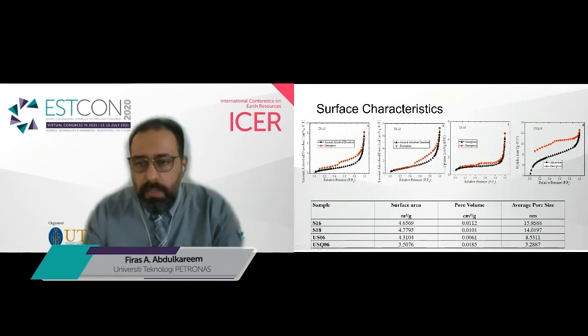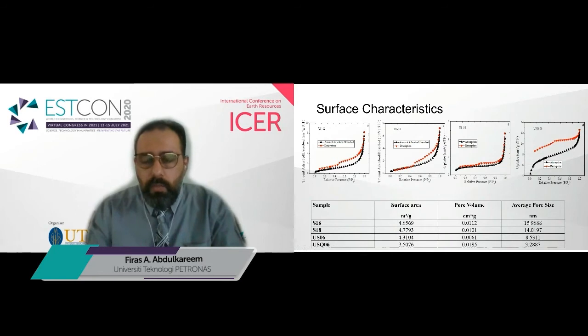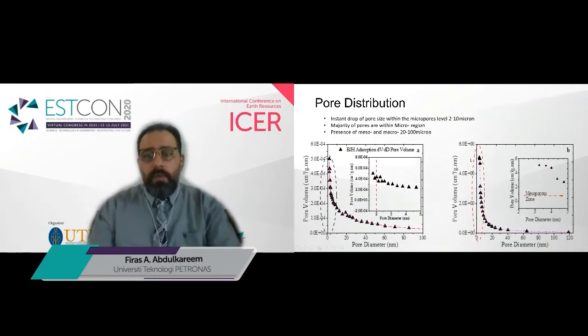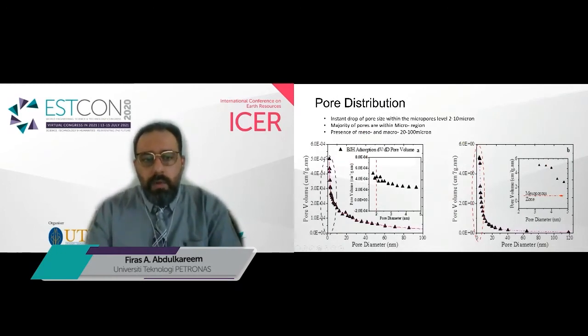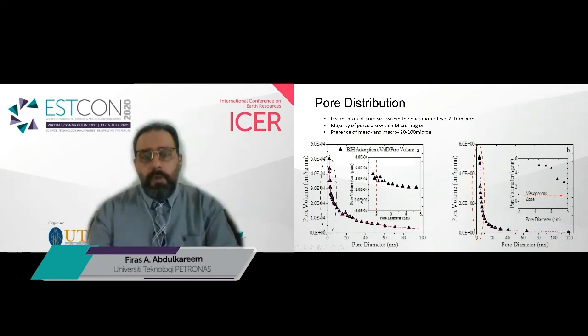And now we need to correlate which are the most dominant factors or parameters in terms of the physical-chemical characteristics of shell, or any porous material indeed, compared to the total organic content. So on the pore distribution, we can see that for all the samples we have a micropore distribution, and most of the pores are accumulated in the micropore region, with some presence of meso and macro regions. But the highest amount of pores is in the micropore region.